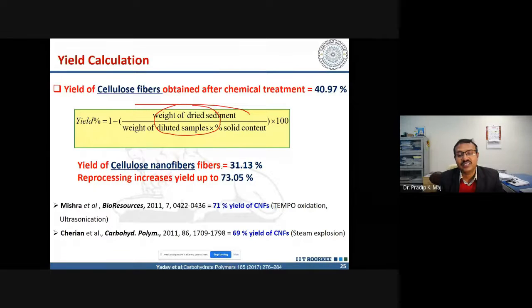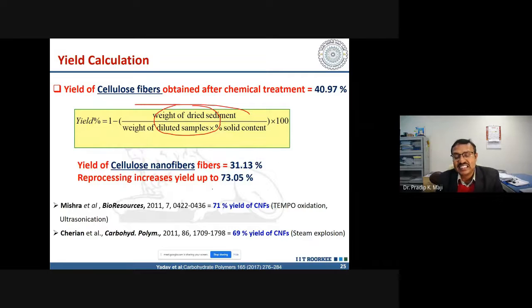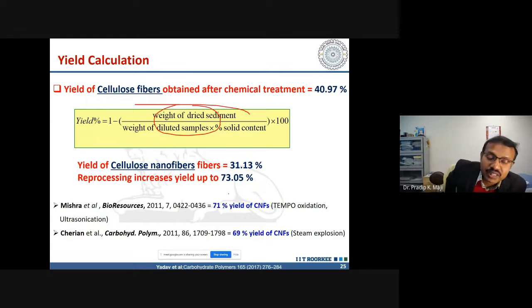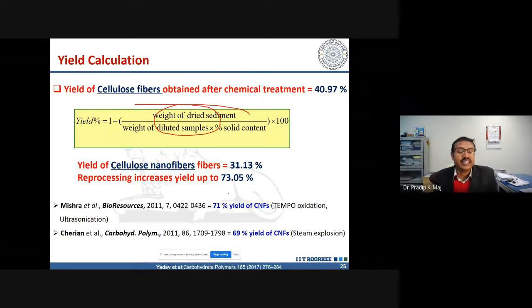The yield of cellulose nanofiber is 31.13%, and with reprocessing it increases up to 73.05%. This is almost, or a little better than, the already reported value by Mishra et al.